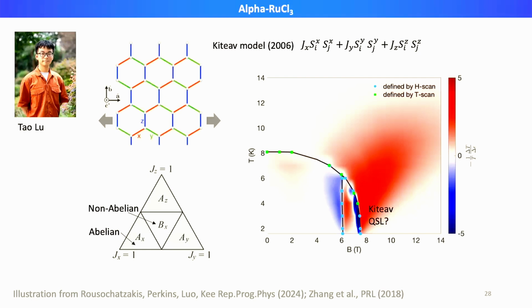And this, in principle, should give us information about the entropy in the system. So what we've identified is that near the region of the phase diagram of ruthenium trichloride where the quantum spin liquid phase is proposed, we do see a large accumulation of entropy near this region. And one of the really cool experiments we can imagine doing, which may or may not be exceeding the ability of the strain we can apply reasonably in our lab, is that by applying strain to break the symmetry between Jx, Jy, and Jz, right? We might be able to tune our system into different regions of Kitaev's phase diagram, where the different regions all have different types of unconventional low energy excitations.